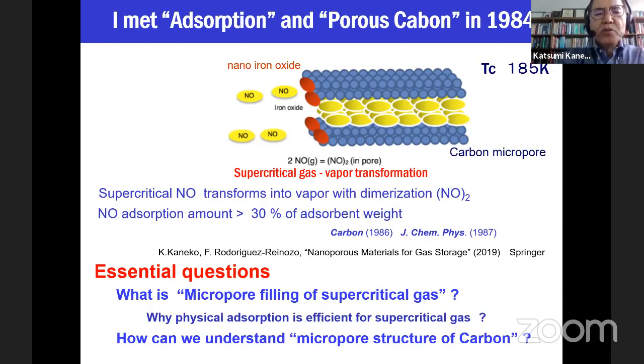At that time, I noticed nitrogen monoxide has unpaired electrons, so it is a radical. Then I thought I should use such an unpaired electron for fixation on some solid. Then I put nanoscale iron oxides near the carbon pores. At that time we didn't say nano, but at this moment we should say nanoscale iron oxides, deposited on the entrance of the carbon pores. Then nitrogen monoxide approaches here, and spin-spin interaction occurs because iron oxide Fe3+ is in a high spin state, so they interact strongly magnetically. Then nitrogen monoxide, the monomer, converts to the dimer,